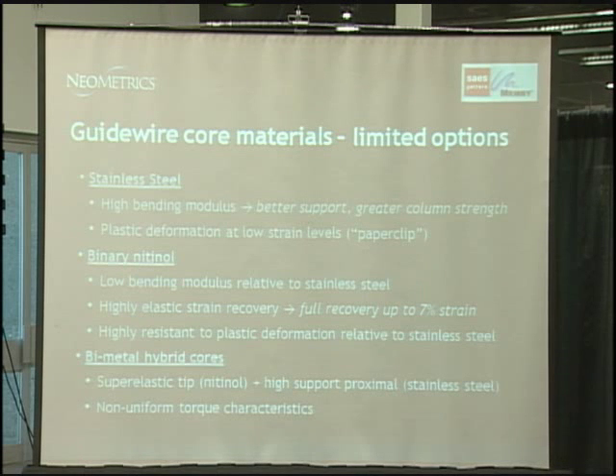It has a very low bending modulus. It's very soft material, but it is highly elastic, highly recoverable, even upon fairly high strain conditions, which can be as high as 7% strain. And of course, that's a function of the wire diameter.